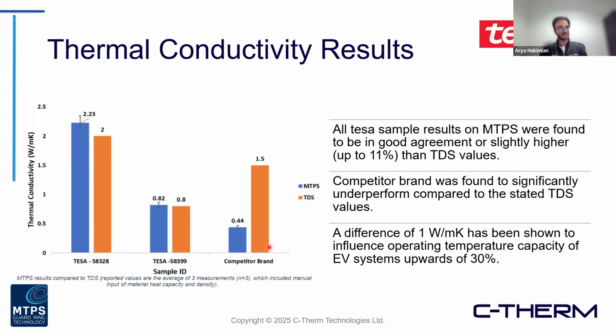But then when we actually tested the competitor brand sample, which was spec'd at about 1.5 watts per meter Kelvin, our measurements were coming in at about 0.44. So this was confirming what they had been seeing in their in situ testing, but also an example of why it's very important to verify some of these technical data sheet claims. Although the technical data sheet does give us a baseline value here, they're not all created equal.